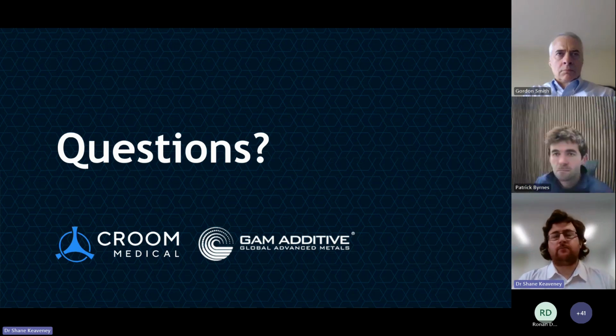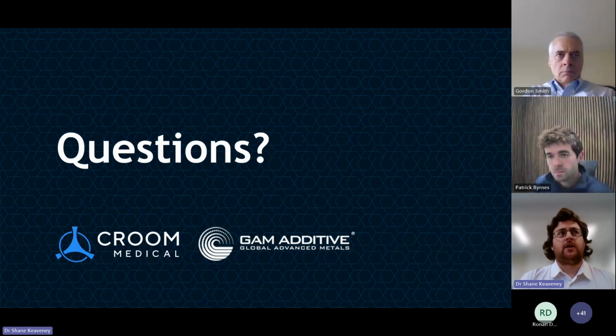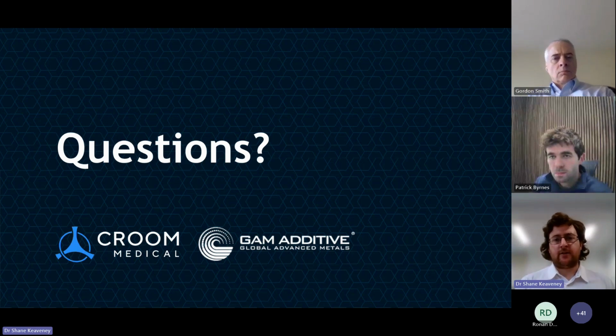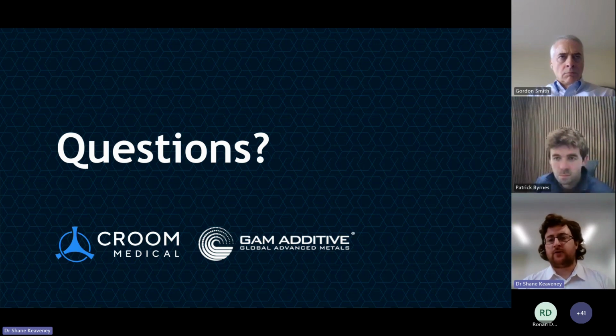Smallest pore size. I mean, it depends what someone wants there, really. We've gone down to around 100 to 200 microns, very, very small. Typically, though, we're actually aiming for a little bit larger than that. In terms of strut diameter, again, between 150 to 200 micron would be the smaller range that we can achieve. But for us, we haven't focused on going that small on the pore size, so we could probably look at that further. We've been focused on a little bit of a larger range, above about 200 micron on strut diameter. So that's been our focus for the moment.